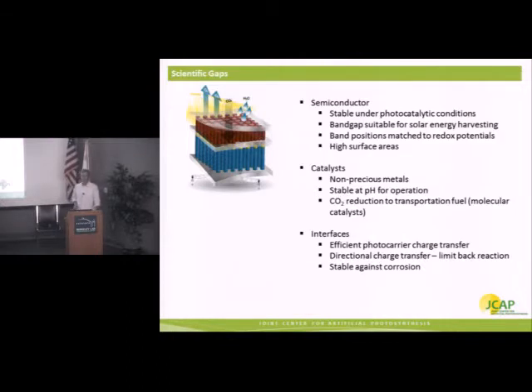So there's a number of scientific gaps associated with this device. We can draw these pictures quite well. We can envision in our minds how such a system would work. But in reality, we have a number of problems. With the semiconductor itself, it has to conform to three major things all at once. It needs to be stable under the conditions for photocatalysis to occur. The band gap has to be suitable for capturing the solar spectrum with a high degree of efficiency. And the positions of those valence and conduction bands have to be well suited for driving the reactions that we desire. Often, these materials also require high surface areas to improve efficiency.